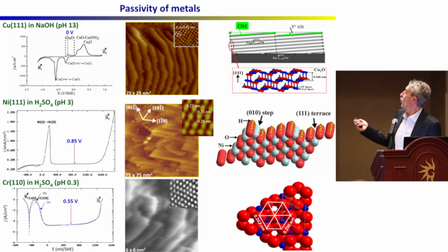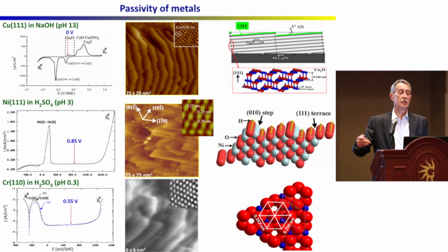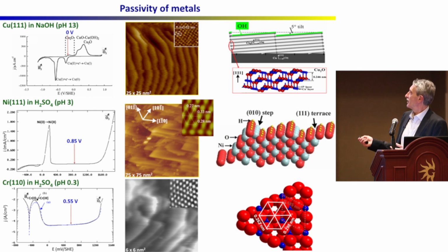And the layer of OH, this is not derived from in-situ STM. This is derived from ex-situ XPS. And there are also other groups who have seen that even before we did for the ex-situ XPS, like Henning Strehblow, for example. So to make a long story a bit shorter, we did that also on nickel, and similarly crystallinity,